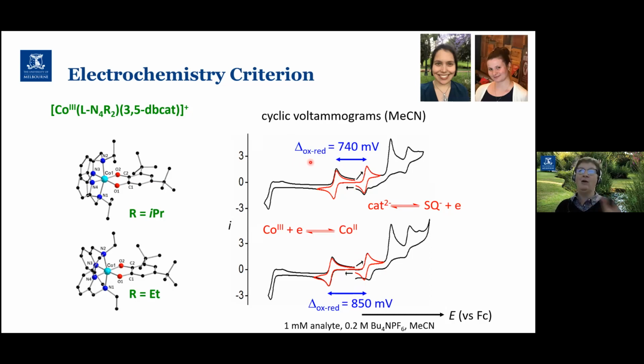We've looked at lots of our complexes and literature complexes. We've come to the conclusion it's obviously condition variable, but in these sorts of conditions in acetonitrile, a delta ox minus red of about 750 millivolts, that separation between the first metal process and the first ligand process, is what we need to access a VT transition at reasonable temperatures. Once those processes become further and further apart, that's a proxy for the energies of the orbitals. They're becoming further apart and you're not able to access that transition. So that's a really handy rule of thumb for us to use in the lab when we make a new complex, to see whether we think it'll do a VT transition or not.